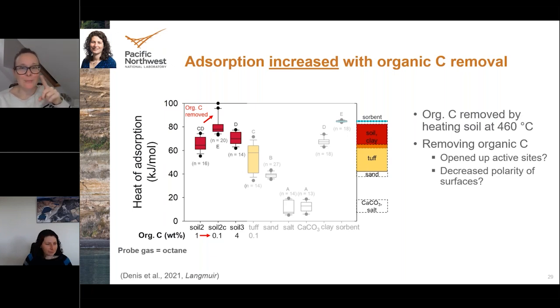I have to agree. Sorry, I have a small comment on this. Yeah, because that's also great. I showed that surface energy profile of zeolite at different temperatures, and what we also observed is that at 400 degrees C, the heterogeneity starts to have a little bit higher distribution on the surface, and maybe this, what you mentioned, that higher energy sites open, so that increases the heterogeneity of zeolite. And the answer for this, I think, is very complex. There are so many things happening, and the heterogeneity is changing with the temperature, and more high energy sites become available, which can affect this. So it's a complex thing, but it's really important to investigate and have some real experimental data at that condition, and then make the model based on those.